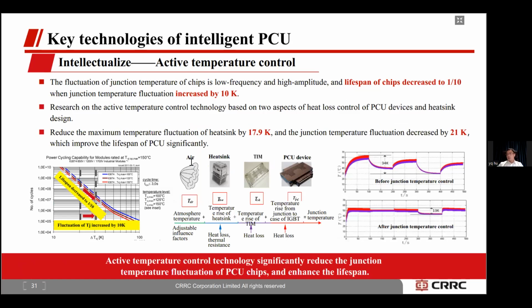As for the thermal management part, we managed to attain the active temperature control. As the fluctuation of junction temperature of chips was low frequency and high amplitude, we found out that the lifespan of chips decreased to 1/10 when junction temperature fluctuation increased by 10 K.